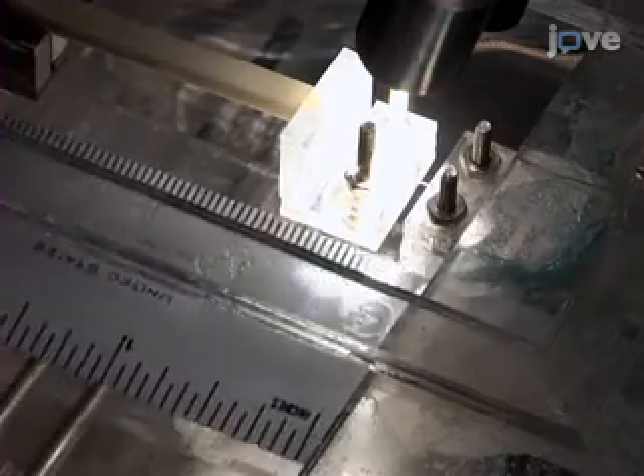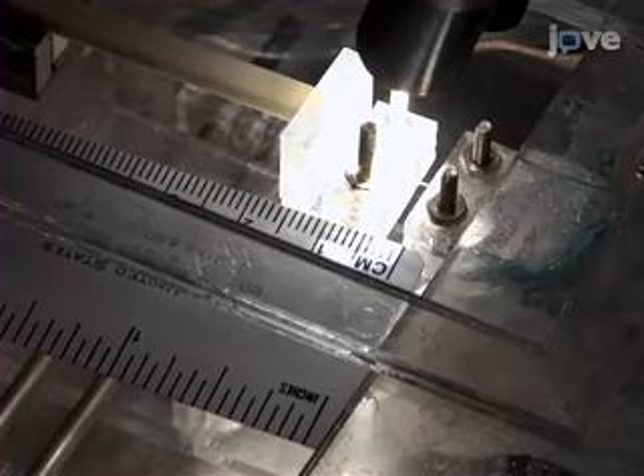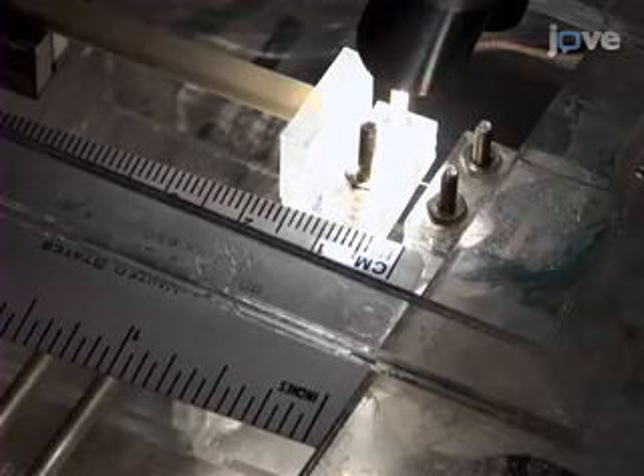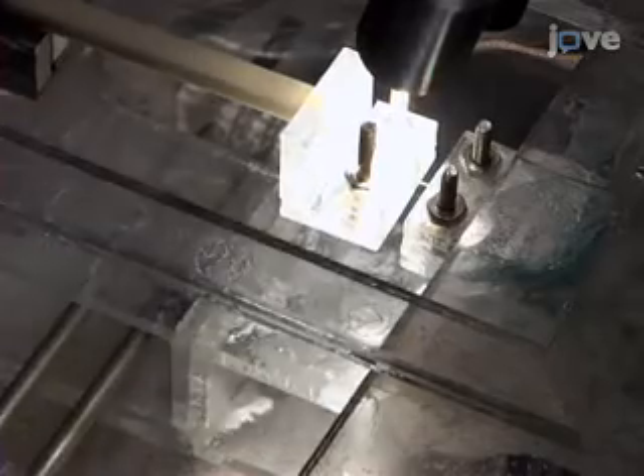Now adjust the sample position such that the distance between the clamps is 3 mm and the end of the probe is placed into the fixed clamp. The 3 mm length between the clamps is the gauge length of the sample to be used in later calculations.